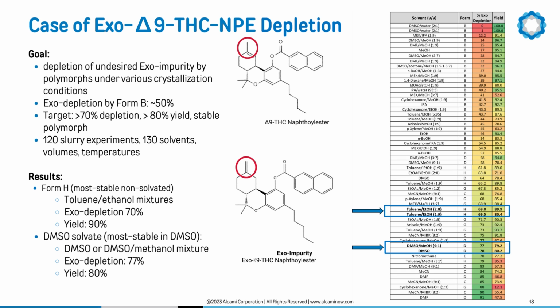Depletion of the most stable form H and some of the other solvates were at higher levels as compared to those of form B. For instance, crystallization of form H from 5 volumes of toluene ethanol in 1:9 ratio landed at 70% depletion and 90% yield. Another example, crystallization of DMSO solvate from 40 volumes of DMSO methanol in 9:1 ratio resulted in 77% depletion of the impurity and yield of 80%.